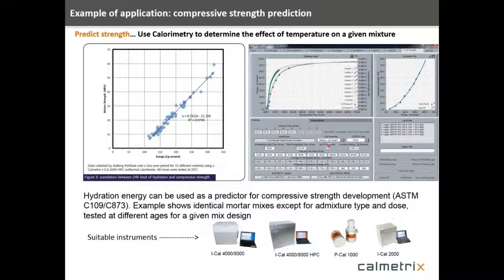And the way that we do that is we first build a model. So this does require you to build a model first, where we run the experiment using the isothermal calorimeter and generate the heat flow curve. But you also then take that same basic mix and generate the compressive strength at discrete data points using the standard ASTM technique of breaking your cylinders to get that data. And then you basically create a model that relates the compressive strength at a particular time to the joules per gram from the calorimetry data. So we do that at various discrete points and create a model.